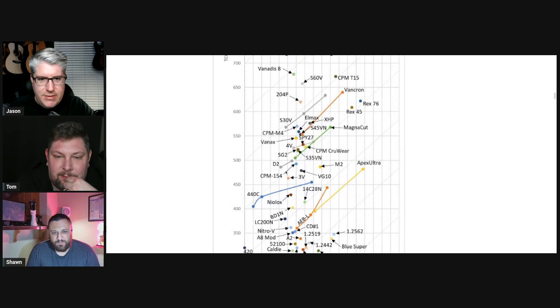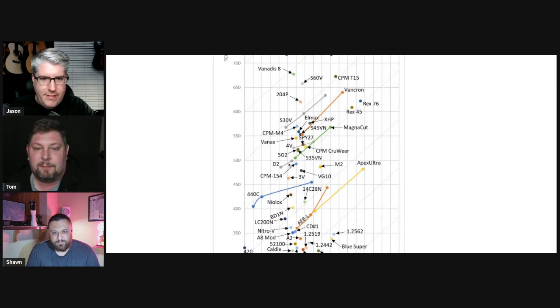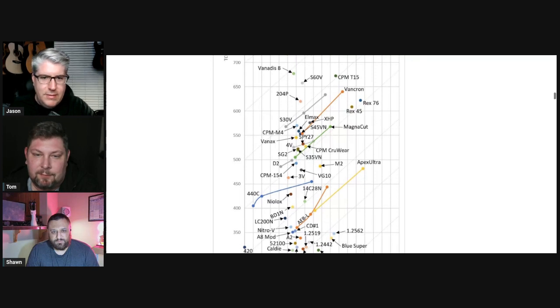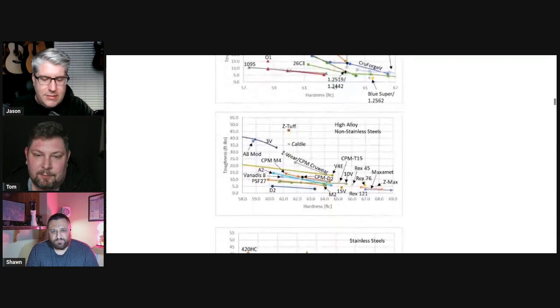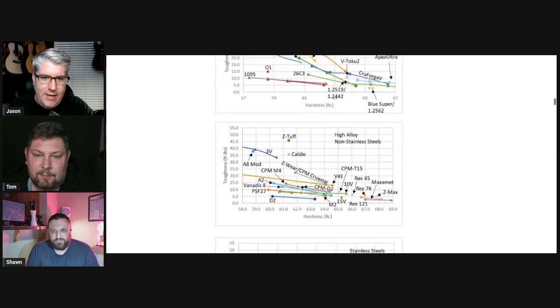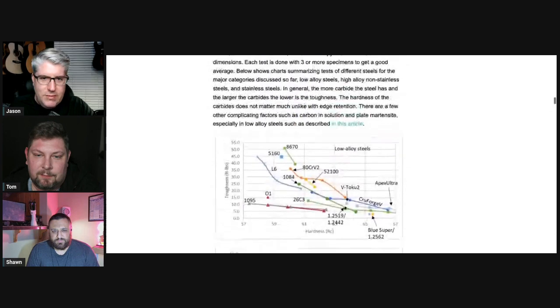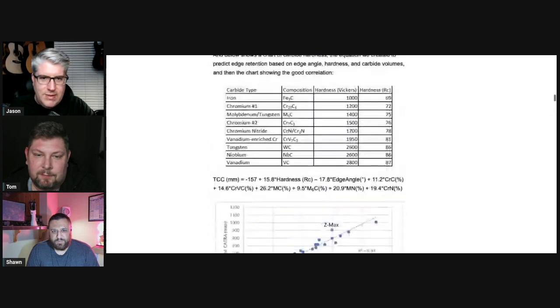So it looks like D2 is around 450 to 500, or 475 to 500, depending on the hardness. You'll notice, guys, as the hardness increases on the knife steel, the edge retention goes up. But back here on our toughness, as the hardness increases, what do we notice? That it always trends down in toughness. So you can have tough, or you can have edge retention, but it's difficult to have both at the same time.